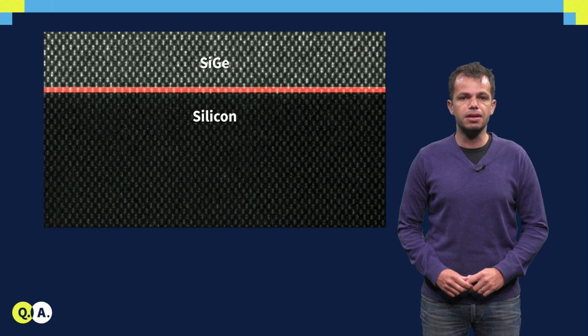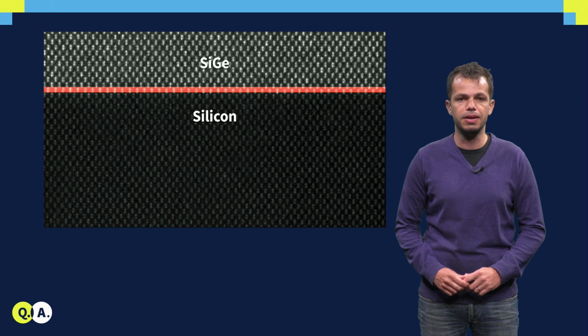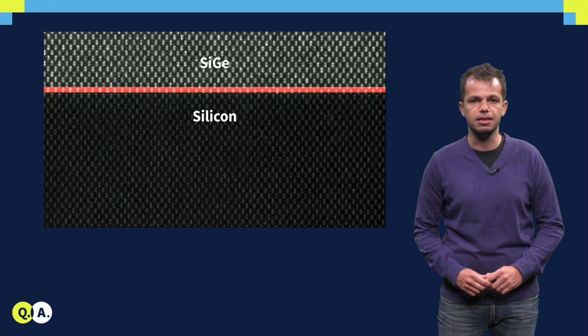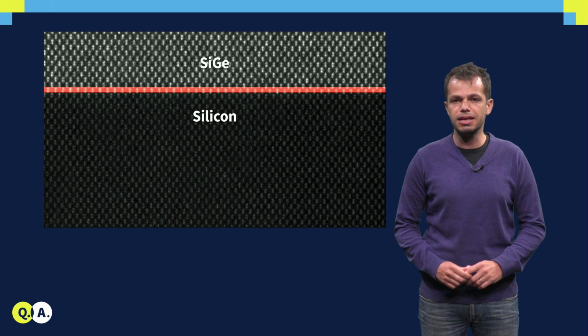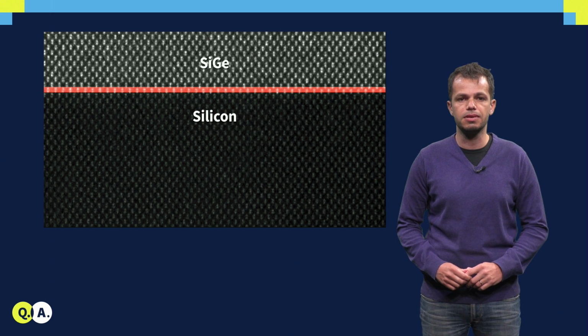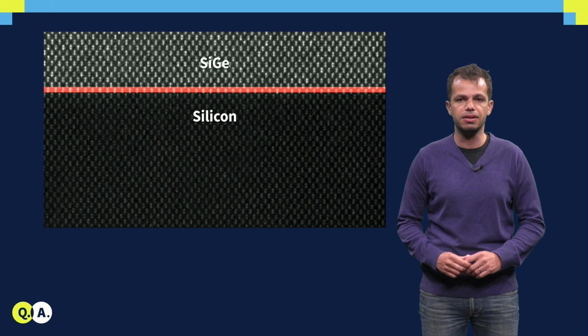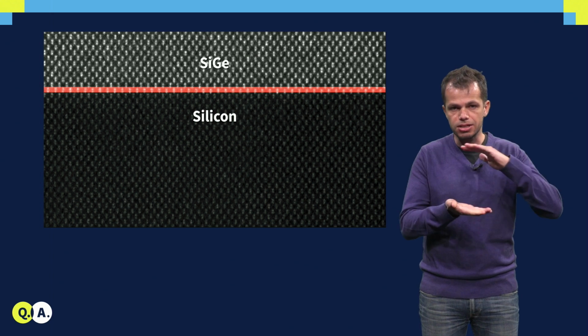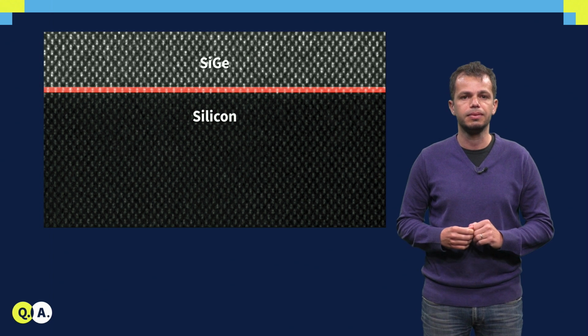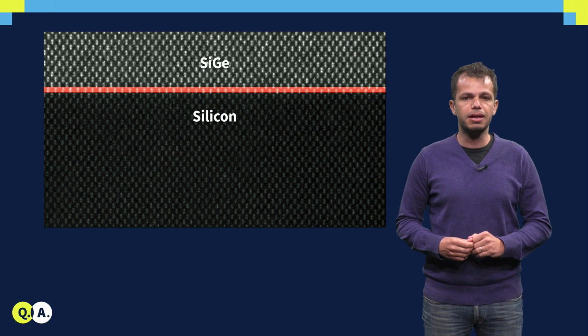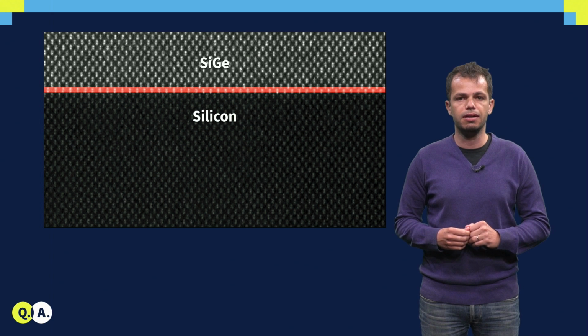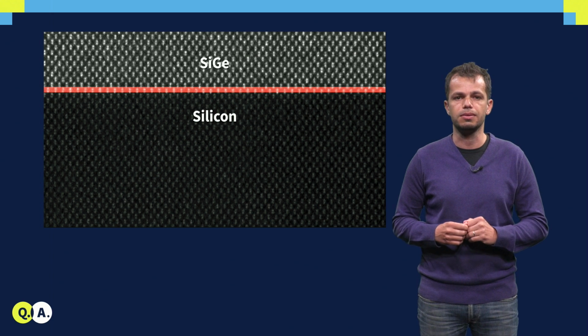For example, you see here the perfect atomic arrangement of silicon and germanium atoms in the critical interface between silicon and silicon germanium. The lattice spacing is exactly the same at both sides of the sharp interface, indicating that the CVD process successfully strained silicon to match the underlying silicon germanium. The fact that we are able to make crystals with such precision and very little imperfection is a key asset to then make good qubits.